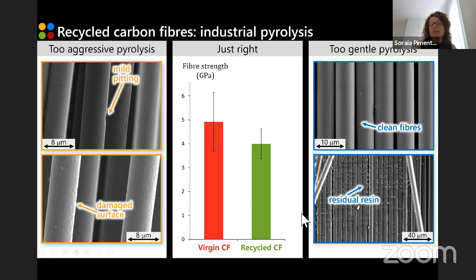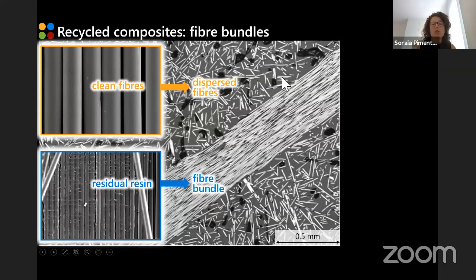Now, these residual bundles that you can see here on the right-hand side, held together by residual matrix, can be seen as a defect, but they are not necessarily so. When we reimpregnate the recycled fibers with a new matrix to manufacture a composite, we can very often see this type of microstructure where you have dispersed filamentized fibers that are very clean after the pyrolysis process, but also some fiber bundles that are held by that residual matrix.